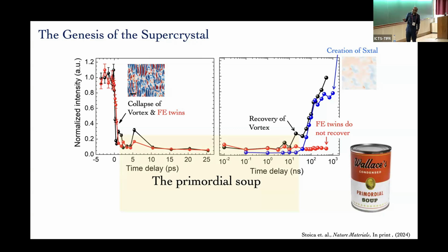Okay? This primordial soup is hot because you hit it with a lot of power, but hot is not enough. You hit it with any random laser, it won't work. It has to be charged. Remember, with a wider band gap, higher than the band gap, you're injecting carriers. That's very, very important. And so then it's hot and charged, and then it forms a metastable soup that normally would not exist at these temperatures. It cools down, and then a crystal comes out of it. This is the supercrystal. Okay?